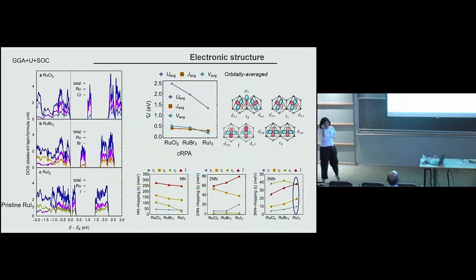So what we did is, as a calculation, you usually do a calculation for a pristine system, so a perfect system. Let's assume that we have perfect ruthenium iodide, and we take, of course, the crystal structure that has been given, but we don't have issues of vacancies or any other type of impurities. So if you take now these structures and you do an electronic structure calculation, what I'm showing here is for the three materials, basically what you find is that the systems are Mott insulators.